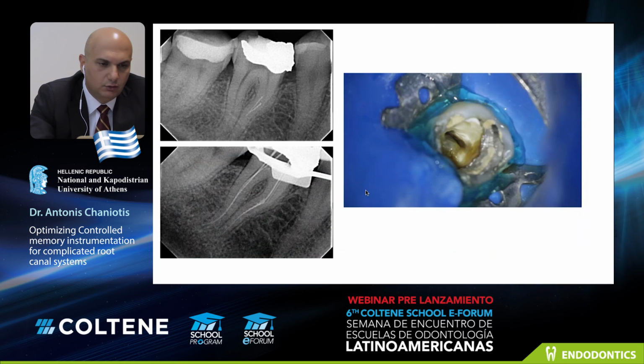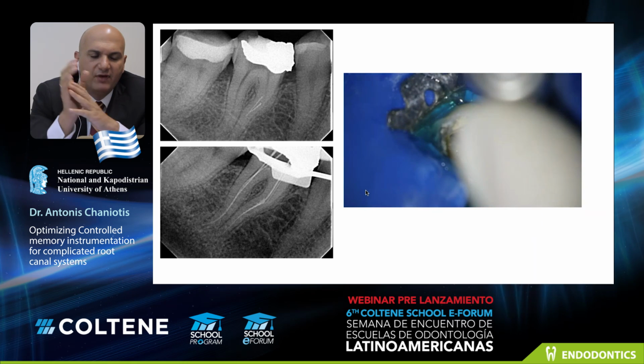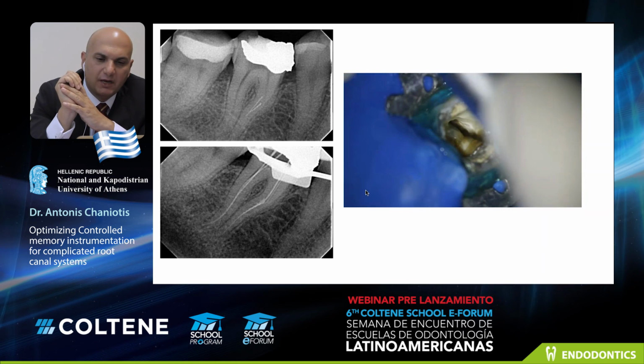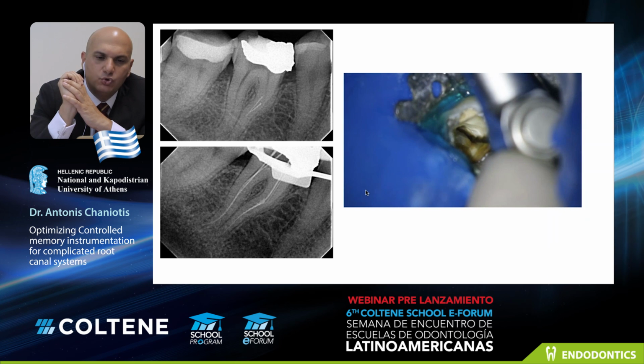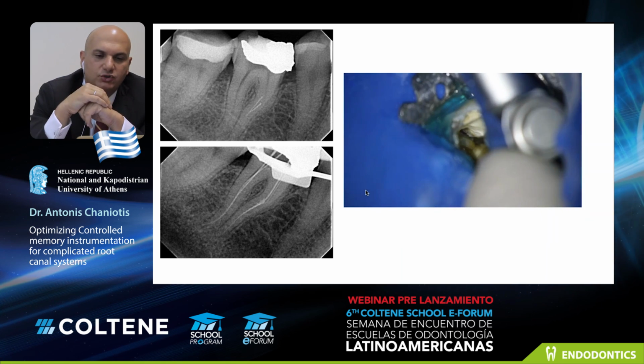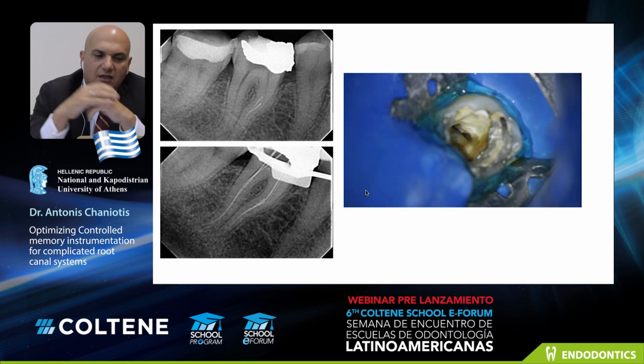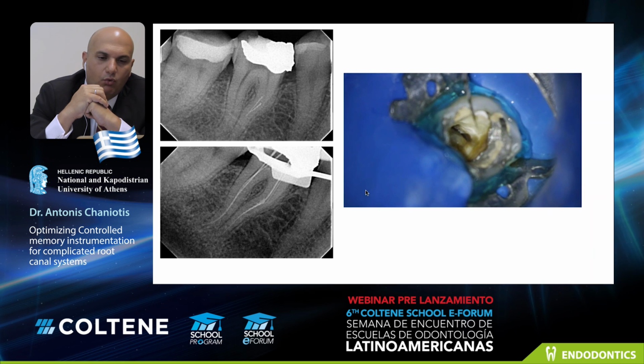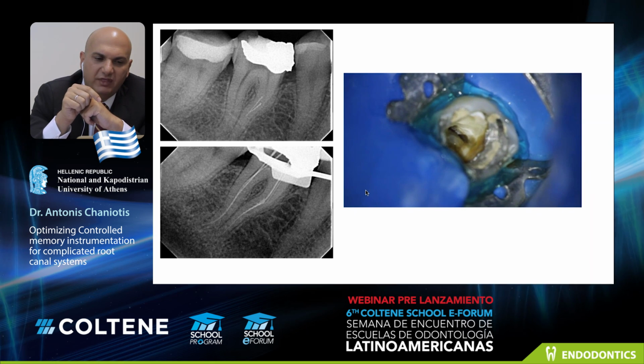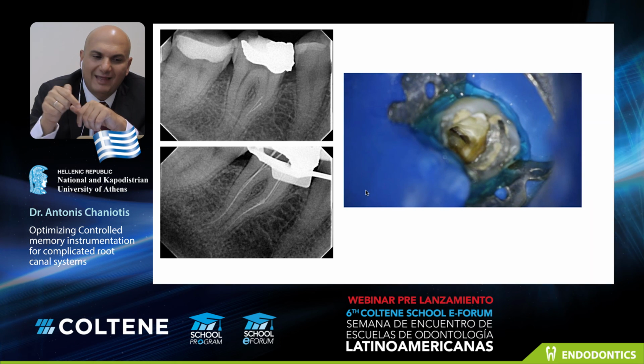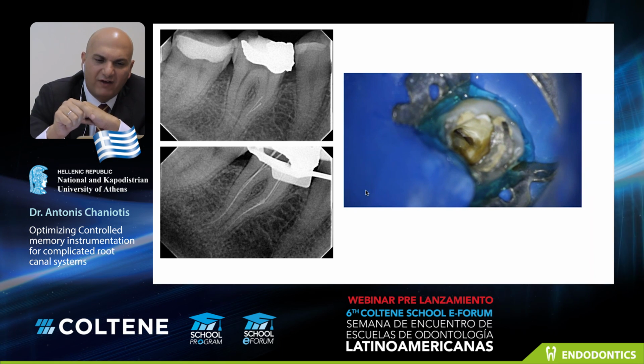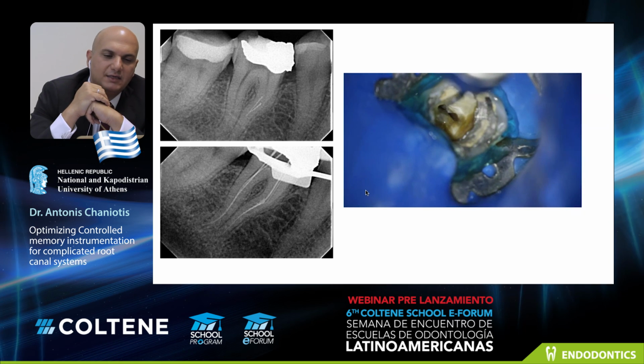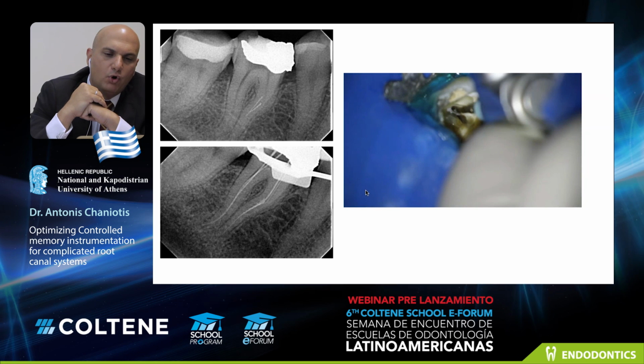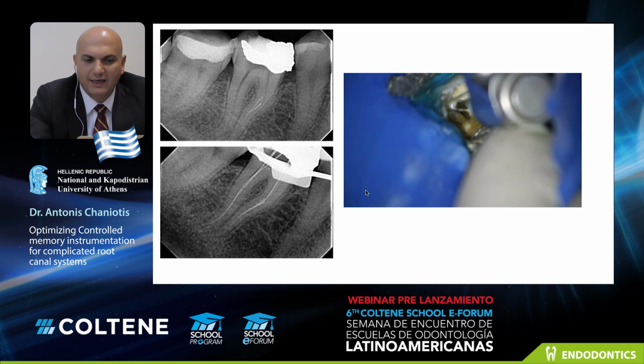In this case, I had two broken fragments in the mesial root of this highly curved mandibular molar. And what I did here, again, whenever I have broken fragments, first I bypass the fragments with hand files, and then I use tactile control activation technique to shape the rest of the canal, to enlarge the space that I managed to bypass. What you need to do, you need to insert the file without activation below the level of the broken fragment, and then activate the file and move it outside of the canal. Sometimes with this technique, you may see the broken fragment moving also, if you are lucky, outside of the canal.